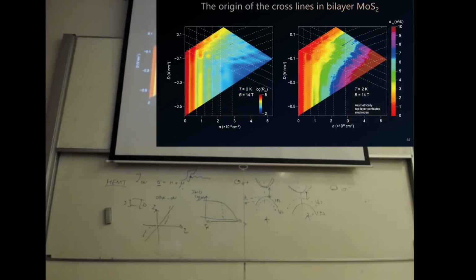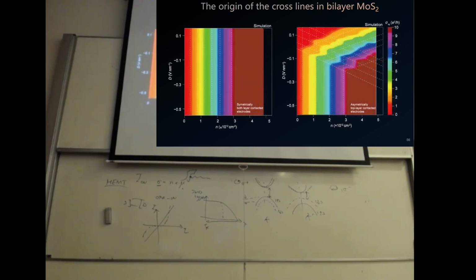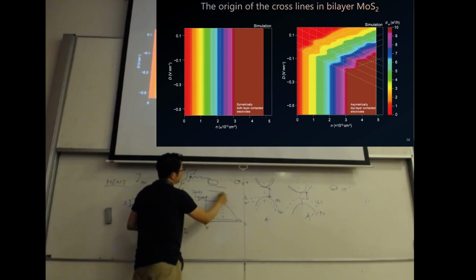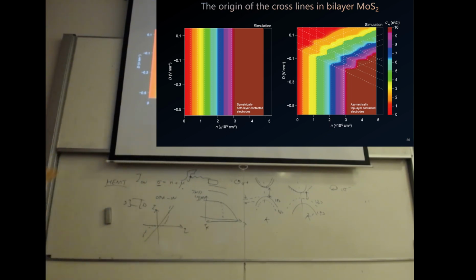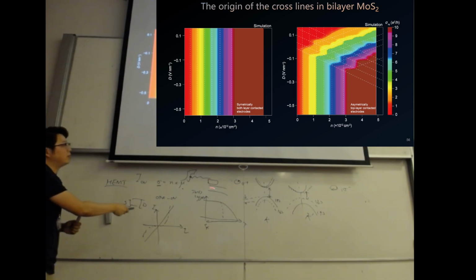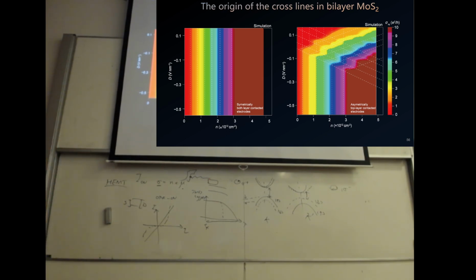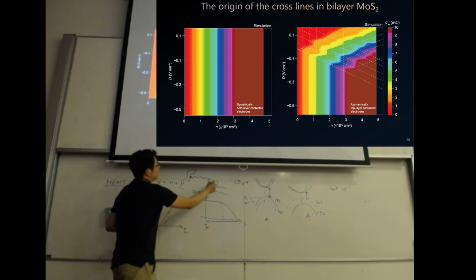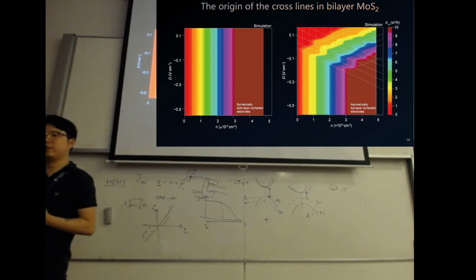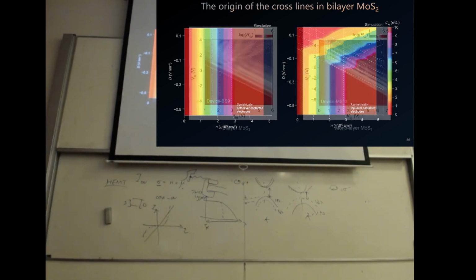They are valley polarized. And since we're measuring bilayer MoS2, there are also some other off-diagonal features we didn't understand at the very beginning. By calculation, we finally realized that it's actually coming from the asymmetrically contacted method. When we have a top electrode contacting 2 layers of MoS2, some of the wave functions are not really probed by the electrode at certain electrical fields, and this can be fully recaptured by simulation. This is a simulation of asymmetrically contacted, and this is a simulation of symmetrically contacted electrodes, so the off-diagonal features are killed. So we now fully understand the system.